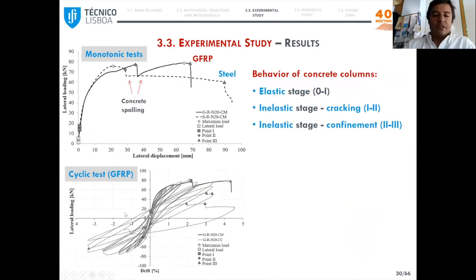Well, in terms of lateral load displacement curves, here you can see the results obtained for the monotonic tests for GFRP and steel column, and cyclic test that we did only for GFRP. So we can see 3 different stages of the behavior: an elastic stage until cracking, then an inelastic stage with cracking progression until spalling of the concrete cover occurred in both columns, and then an inelastic stage where the concrete core remained confined by the stirrups.